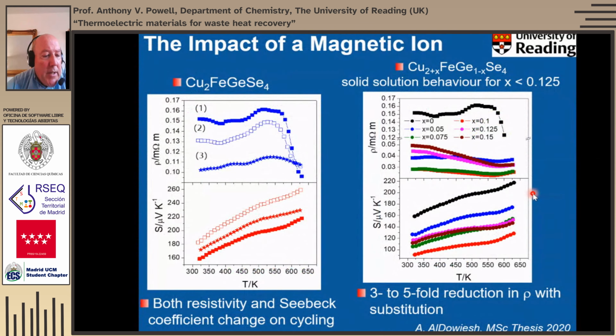Because there's been some studies which suggest that if you have a magnetic ion there, the effective mass of the carriers due to coupling between the electron and the magnetic moment, those effective masses increase, and that can actually be beneficial for the Seebeck coefficient. So we took this end member phase and we essentially tried to do the same process with it, replace the germanium-4 with some copper, which causes the copper to oxidize to copper-2 and introduce more holes and hopefully improve the transport properties.